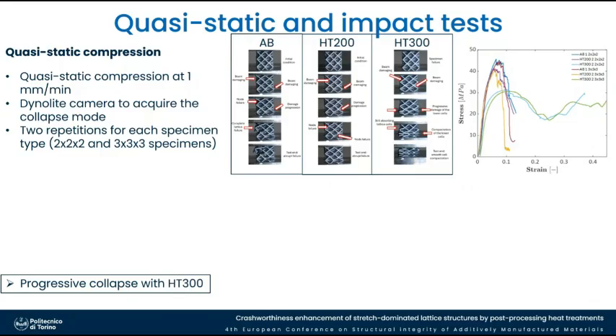And this is observable also in the figure on the right, where you see that the as-built has the highest strength. The 200 degrees is a bit smaller. And then for the 300 degrees, we have this trend of peaks and valleys oscillating around a mean value, because we have a progressive collapse. So when a row of cells collapses, then we have a valley, and then the next one starts collapsing, and so we have again another peak, and so on.